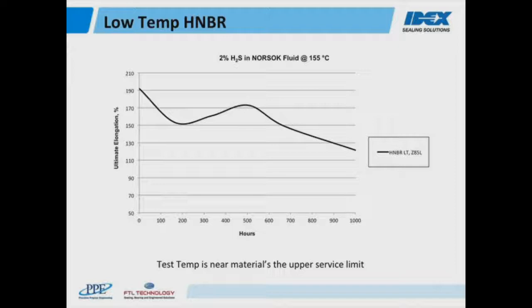In this example, the initial loss of elongation is most likely from the sample's uptake or absorption of the hydrocarbon fluid. Midway through the test, there's some increase in the elongation, which may be some additional cross-linking of the material from the H2S, but this is followed by a steady decline in the elongation as the sample starts to become brittle and react with the hydrogen sulfide.